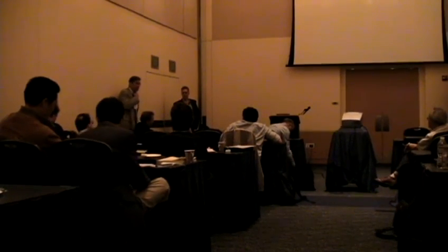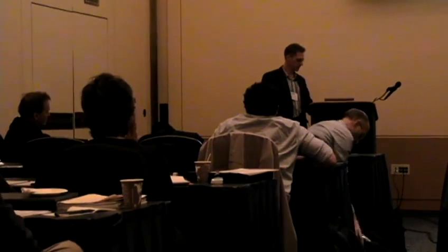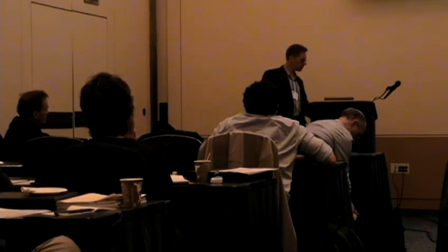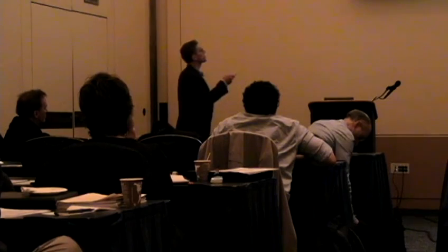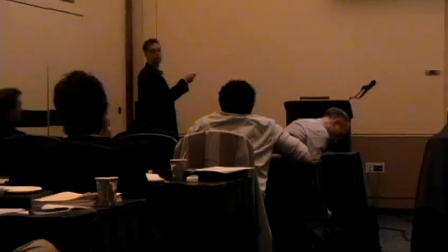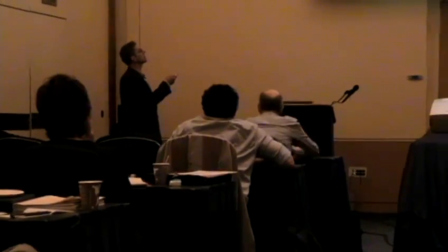How do you get bipolar switching? Well, because you have the three-state system here. The whole point is that I'm going to switch from the locally disordered state to one that is locally ordered with high resistance. But I can't switch directly from here to here. I always have to go through the intermediate state, and this is how you get bipolar switching by going back.